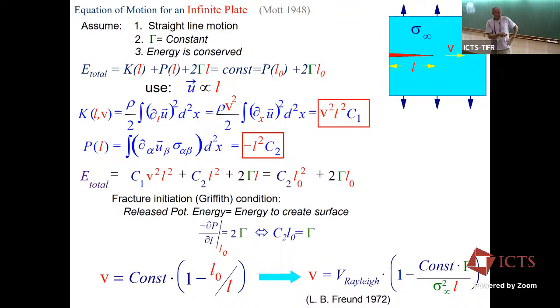And what does this even mean? Okay. First of all, it tells us that v equals 0 when L equals L naught. Well, that's what we assume. That's the initial crack length. So if the length of a crack is too small, this would give us v negative, which just means that nothing moves. Okay, so this is our threshold for fracture. There's a critical length, which is called the Griffith length in the system. If cracks are too short, you won't get propagation.